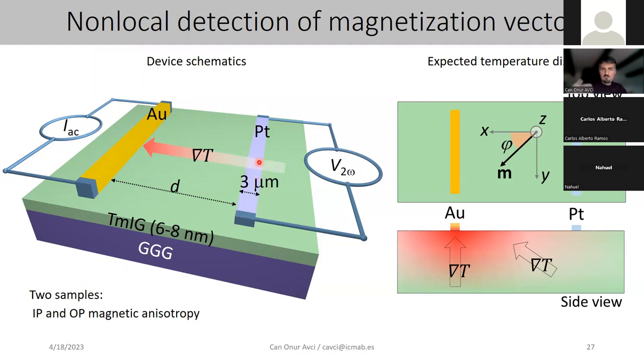And platinum has a large spin Hall effect, therefore it can detect the spin current that goes into the platinum from the bottom. Here I need to say that we are interested in purely thermally driven signals, and not the long-range magnon transport that's usually required, with spin current injection from this side. But this gold is basically disconnected from the film by some oxide, so there's no spin current injection from it, purely thermal.